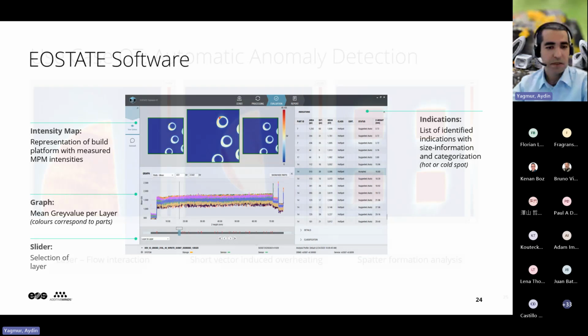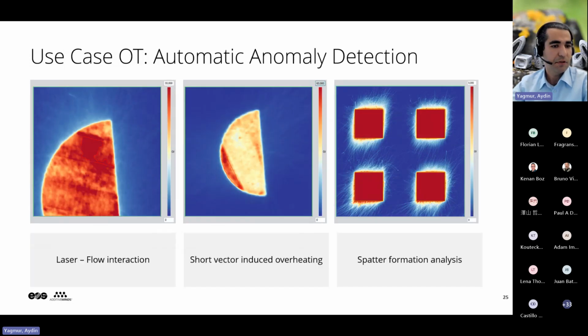Let's have a look at what kind of anomalies can be detected. For example, here you see with the red line the anomaly on the part, which is coming from the laser flow interaction, was detected by our OT. We have different detectors that can be optimized, and we can detect this area. This is documented. The intensity of this area is documented, and we can compare and evaluate the formation and the severity of the indication. Here is again an example of short vector induced overheating. These areas can also be detected.